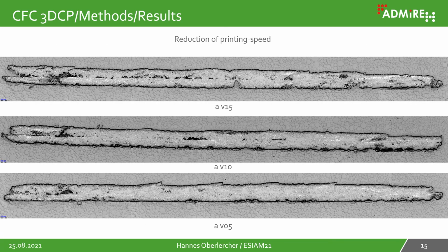Here you can see the results of the second experiment, also with the reduction of the layer height and of the printing speed. The first sample, with 15 millimeters per second, has a high content of cavities, especially from the first layer to the second layer. A better result with 10 millimeters per second, and the best result with 5 millimeters per second. The fibers are pretty well distributed inside, with a low content of cavities from the first layer to the second layer, and the lines are also well connected from line to line.